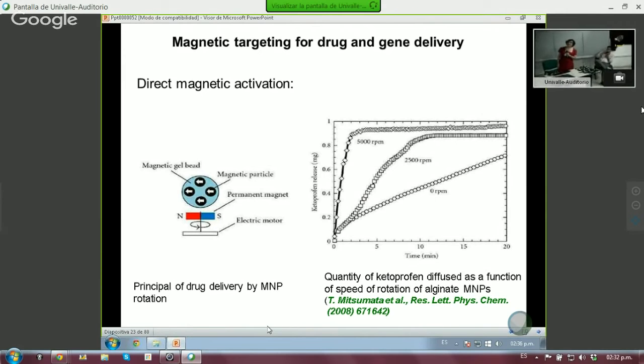And if we continue, here we have a magnetic gel bead. As you can see, we have the magnetic nanoparticles and the permanent magnet, and under the effect of these vibrations everything gets released. Depending on the speed, here are the plots of the release per milligram, in this case of a drug called ketoprofen. As you can see, without any rotation you have a straight line, but you don't go far in 20 minutes. If you have a very strong rotation, you get to the maximum in a few minutes, and the others respond in between the two. So the quantity diffused as a function of speed shows that one can have a handle on how to release it.